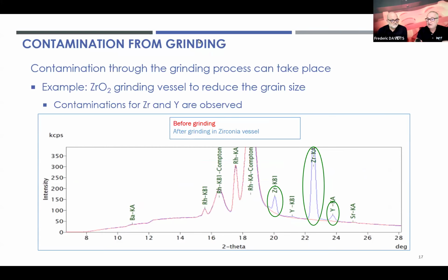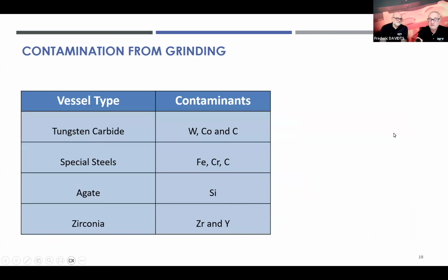Contamination from the grinding vessel can also happen. We can see here an example of a quartz sand that was ground, and the original sample is the red scan. So we can see no contamination. But when I use a zirconia vessel to grind the same sample, I can see contamination appearing, of course, of zirconium, but also of yttrium, unexpectedly. So if you want to analyze, for example, a geological sample in which you want to analyze zirconium and yttrium, you should not use the zirconium oxide vessel.